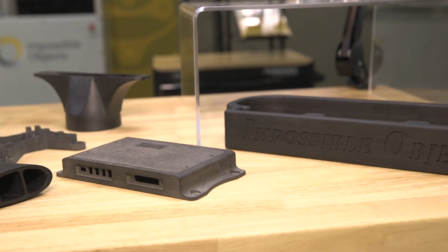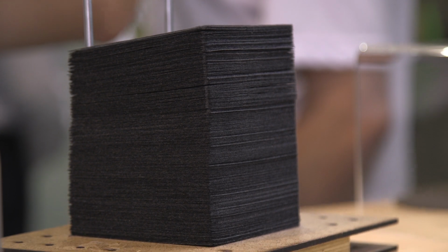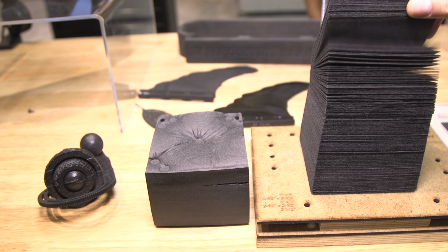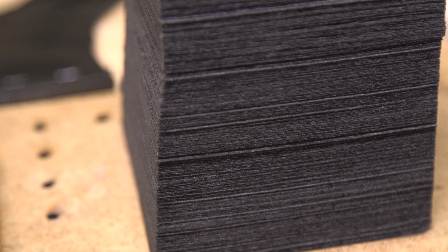We start with a sheet, for example, of carbon fiber, and we print the layer from the CAD model on it with a fluid. We then flood that sheet, which has the layer selectively printed on it with the fluid, with a polymer powder. It sticks to where the fluid was deposited, and we vacuum off the excess powder. We take all the sheets and stack them in register on top of each other. We compress those sheets and heat them to the melting point of the polymer powder, and they fuse together. The portions which have polymer on them make the part, and we sandblast away the carbon fiber which doesn't have polymer on it, and are left with a 3D part.